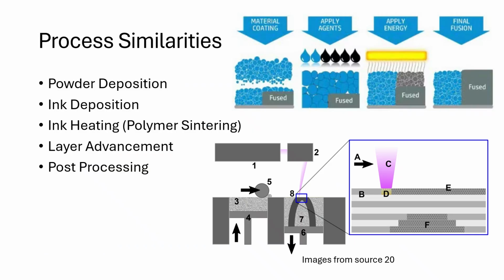Here's why I say it is a good way to think of it as a combination between multi-jet fusion and selective laser sintering. The main process components between both multi-jet fusion on top and selective laser sintering on the bottom are the same as in high-speed sintering. The difference with multi-jet fusion is that high-speed sintering uses only ink and does not use a binder and release agent. With the selective laser sintering process, the biggest technology difference is that the heat is applied in a more global manner and not a laser point.